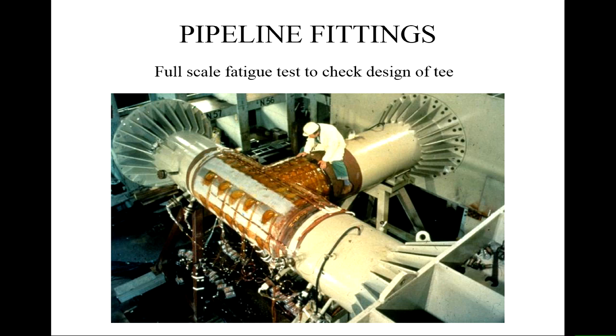Now when you do make a T-piece like that, whether it's a welded T-piece or a forged T-piece, the one thing that you do have to do is check the mechanical properties, and in particular the fatigue resistance of that system. So this is a T-piece which is for the leg of an oil rig, and this is in a test system. So mechanical load, fatigue loading, is being applied to the member on the bottom there, and it's fully instrumented up, you can see here, to measure with electrical conductivity measurements the formation of fatigue cracks on a large scale. And then you have other inspection and test methods that are used at the same time.